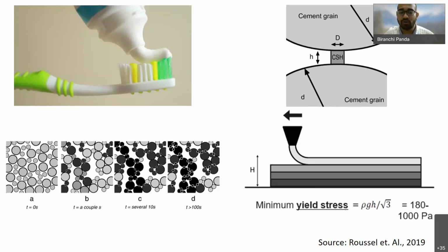They have a van der Waals force of attraction. And because of this force of attraction, once you stop applying any force on the material, it remains in its own position. Now if you want to destroy it, you have to apply some shear rate. So these are very weak bonds which can be easily destroyed. This bond is really useful for the concrete printing process, because it is not so strong that you have to apply high pressure to break it, but its strength is enough to create this yield stress, so that the layers will remain stable after printing. So this is possible using Portland cement, which is commonly used in building and construction application.